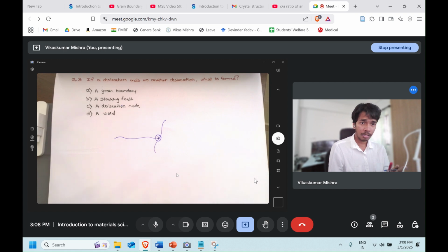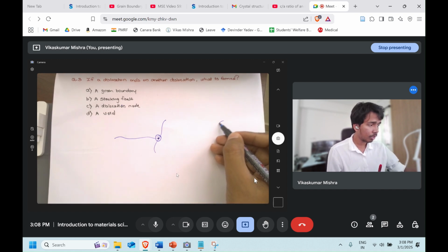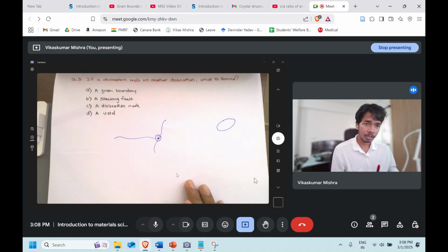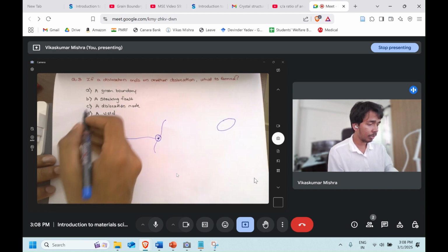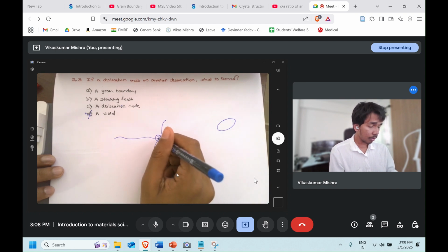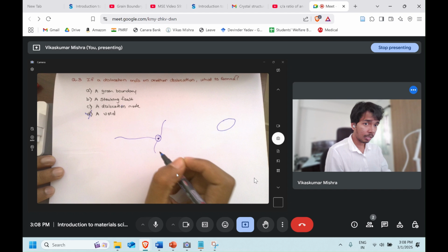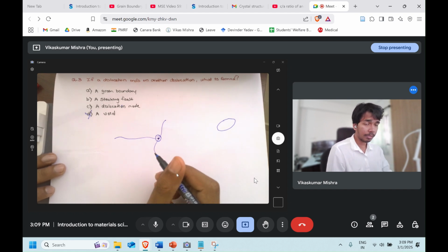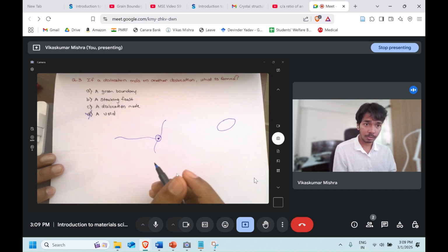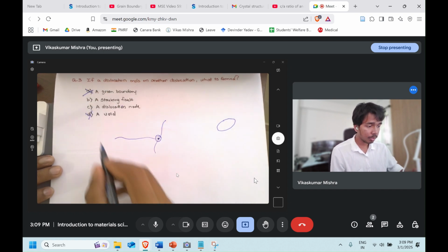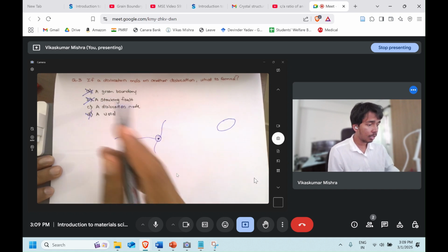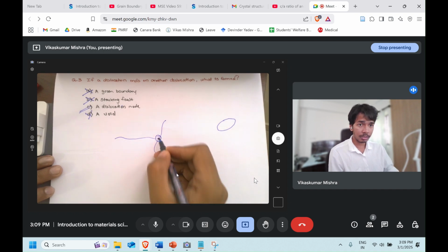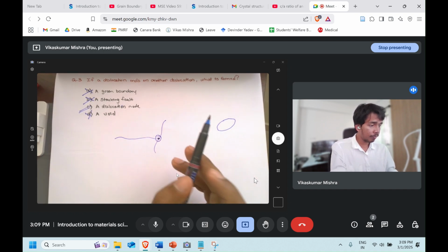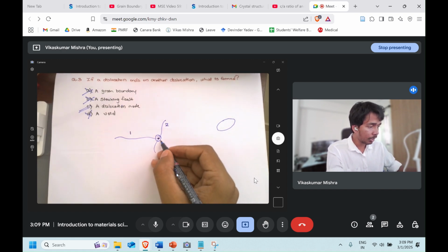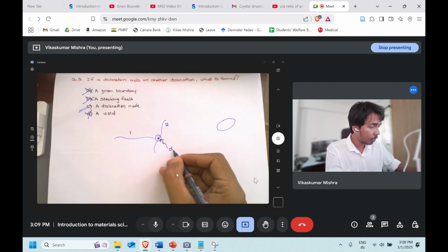For a void, we know we need a large number of vacancies clustered together, something like this. More vacancies will be clustered together, then only we can say that it's a void. So it's not the case. We know one dislocation is intersecting another dislocation. Both are 1D defects, so their intersection will have zero dimensions. So a grain boundary cannot be formed. A stacking fault cannot be formed because it's a planar defect. The dislocation node is the one. The point which is created is a dislocation node. So if one dislocation is ending on another dislocation, the point that has been created is the dislocation node.